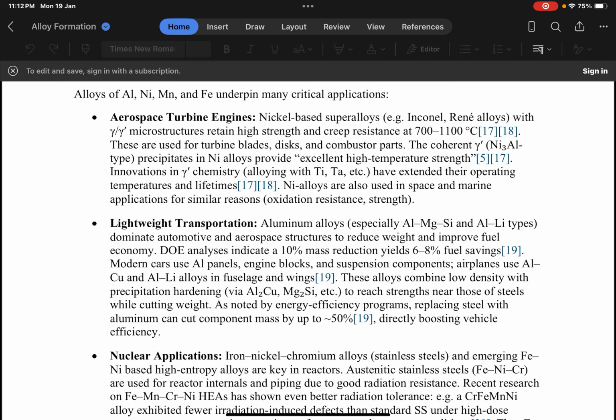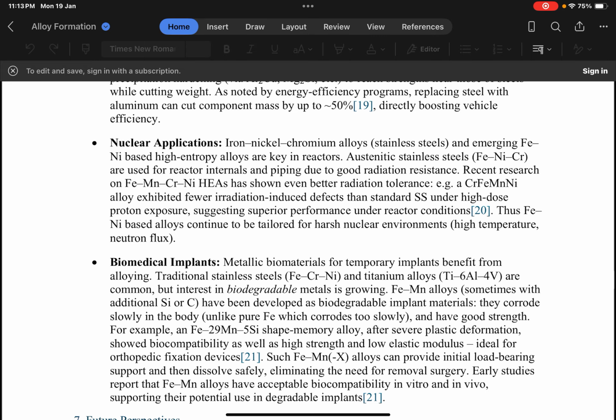Number 2 is lightweight transportation. Aluminium alloys, especially aluminium-magnesium-silicon and aluminium-lithium types, dominate automotive and aerospace structures to reduce weight and improve fuel economy. DOE analyses indicate a 10% mass reduction yields 6 to 8% fuel saving. Modern cars use Al panels, engine blocks, and suspension components. Airplanes use Al-copper and aluminium-lithium alloys in fuselage and wings. These alloys combine low density with precipitation hardening to reach strengths near those of steel while cutting weight. As noted by the Energy Efficiency Program, replacing steel with aluminium can cut component mass by up to 50%, directly boosting vehicle efficiency. The next application is nuclear.